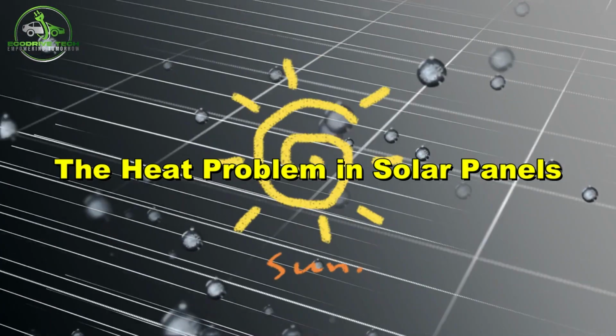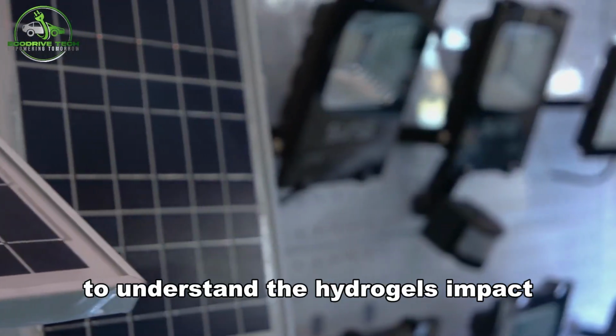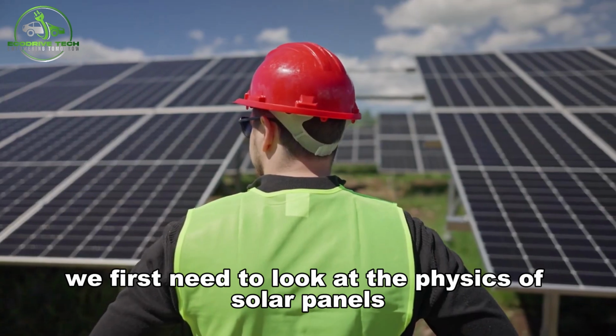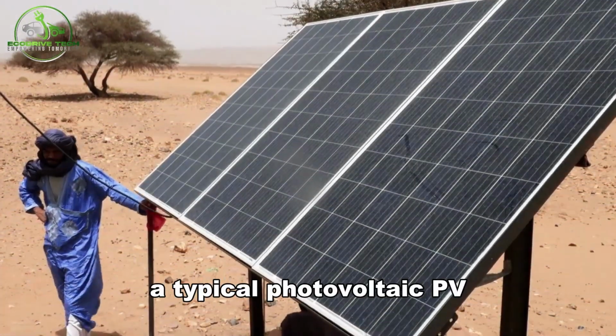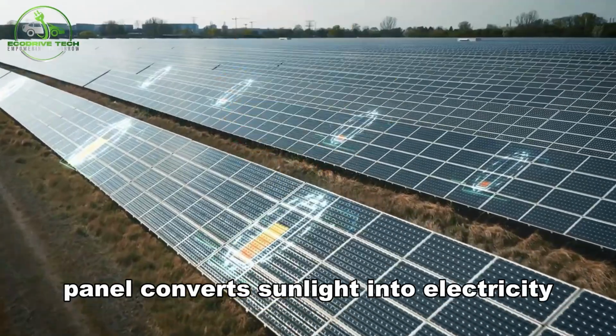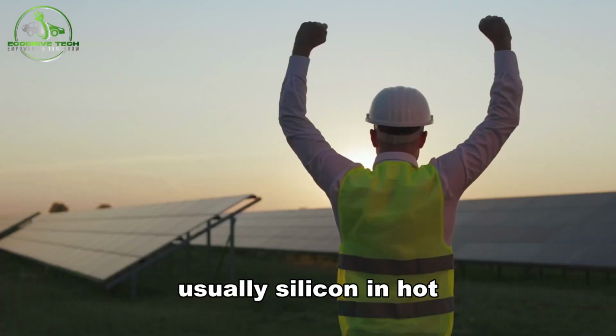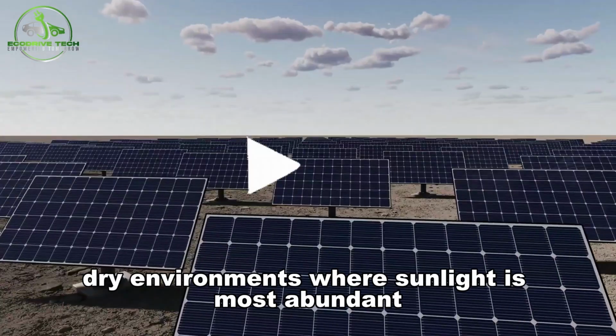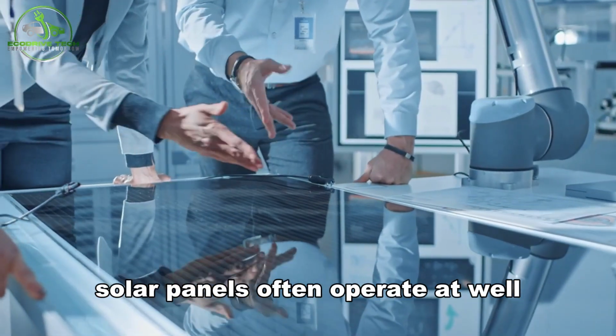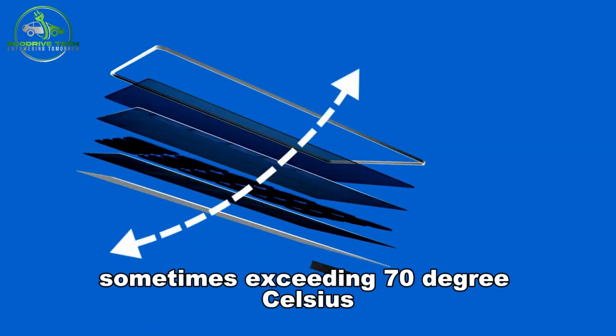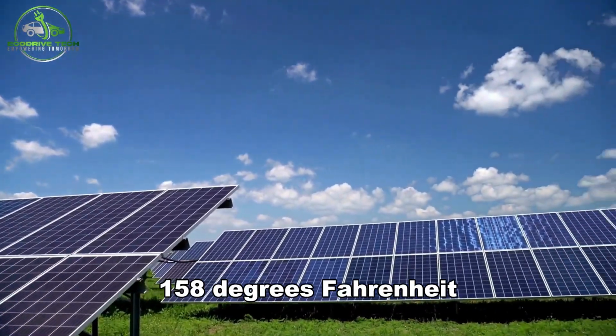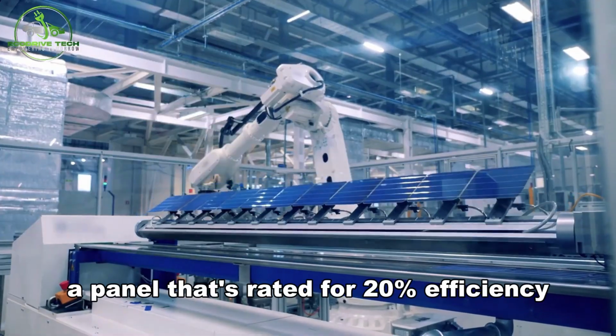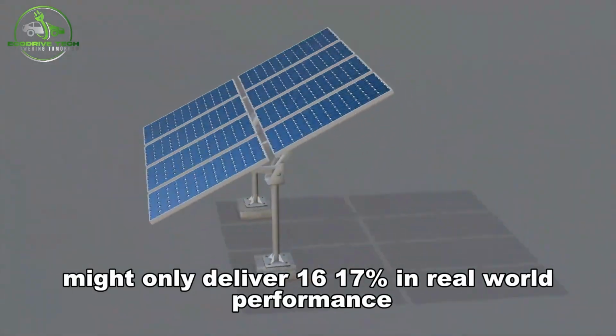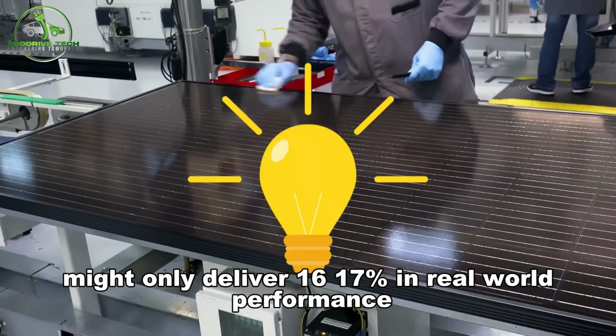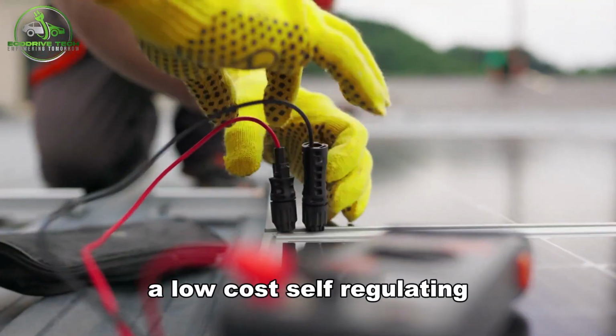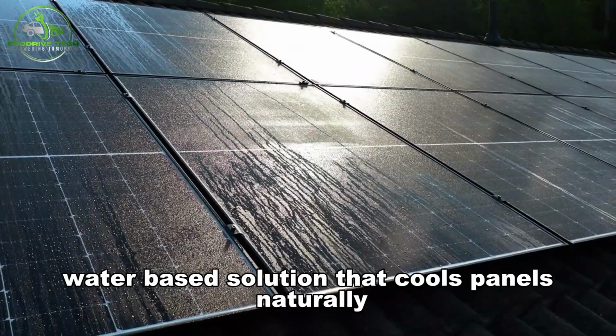The heat problem in solar panels. To understand the hydrogel's impact, we first need to look at the physics of solar panels. A typical photovoltaic (PV) panel converts sunlight into electricity using semiconducting materials, usually silicon. In hot, dry environments where sunlight is most abundant, solar panels often operate at well above their rated temperatures, sometimes exceeding 70 degrees Celsius, 158 degrees. Under these conditions, a panel that's rated for 20% efficiency might only deliver 16–17% in real-world performance. This is where the hydrogel comes in: a low-cost, self-regulating, water-based solution that cools panels naturally.